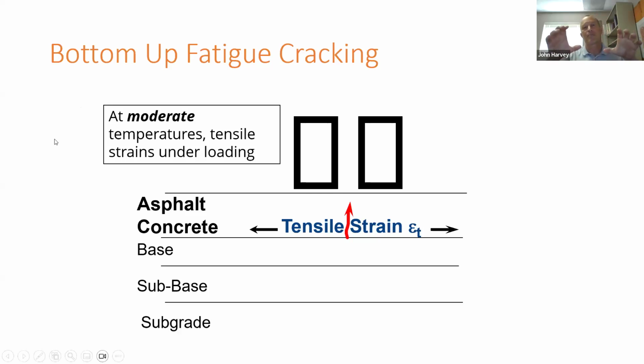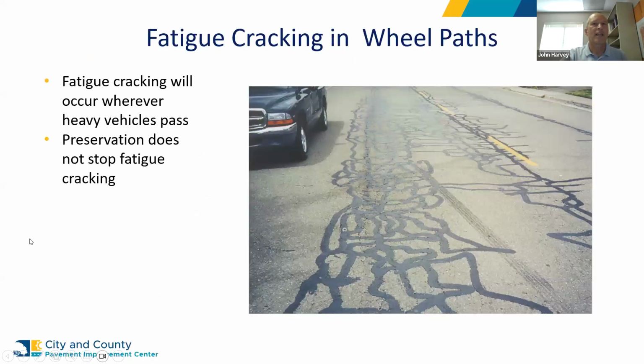what those are doing is they're bending the asphalt. And when they bend the asphalt, that causes tension on the bottom. And these cracks will typically start at the bottom and propagate up. As there are more and more of these loads, you're damaging the asphalt, it creates a micro crack, and then eventually that micro crack starts to propagate up to the surface. Preservation does not stop or really do much about fatigue cracking. Preservation is about slowing age-related cracking.